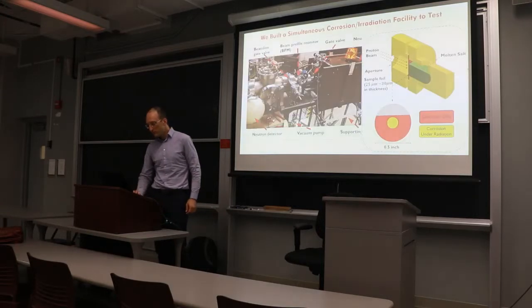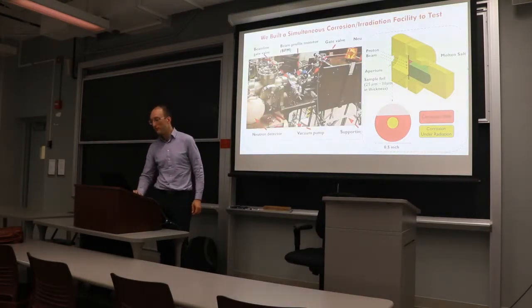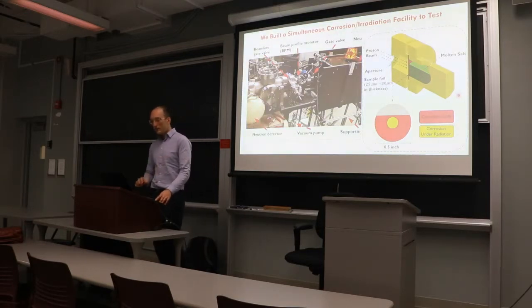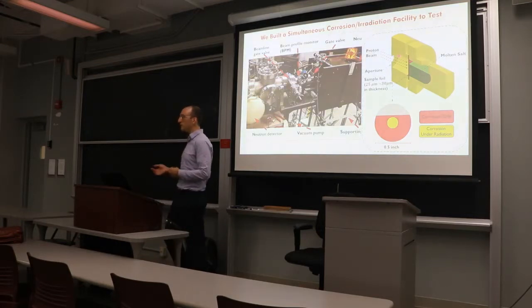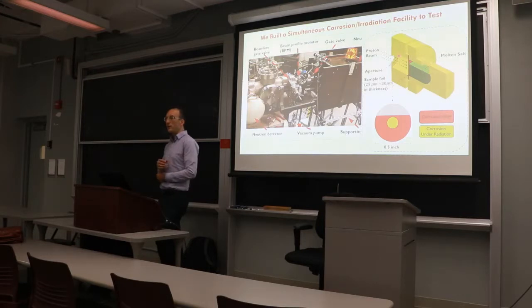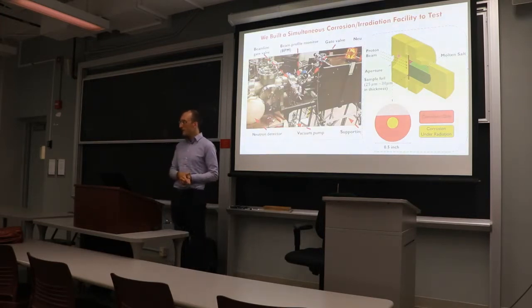We went through ridiculous pains to do that, actually. So we've built a full COMSOL model of this entire beam length. And while we can't put a thermocouple on the back of the sample, we spot welded one to the front, as well as 17 other locations. We just went all out because this was one of the big questions: is beam heating doing something? I would argue that beam heating would accelerate corrosion because you would reduce the amount of radiation-induced segregation. But based on all our COMSOL fitting, the beam heats our sample by about 10 to 20 Celsius, depending on the beam current. As we go down a factor of 2 in the beam current, we're down at about 10 Celsius. Not a big acceleration. Should be about a 2 times acceleration in any Arrhenius-based corrosion rate. That's not going to be present in reactors either.